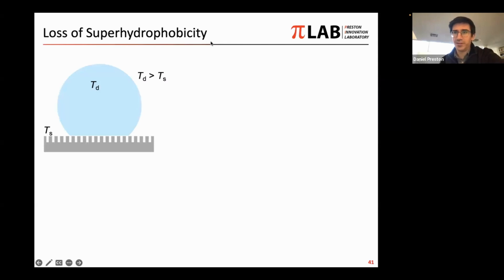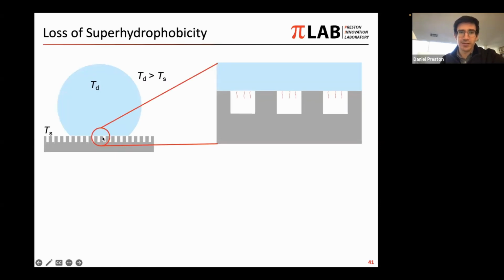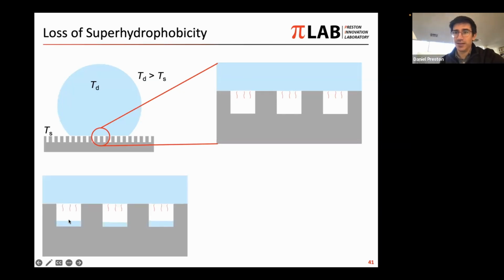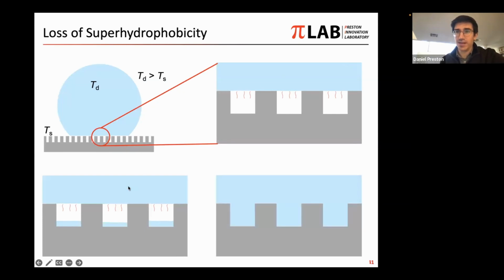And the loss of superhydrophobicity when we have hot impinging water is actually already fairly well understood. So we can zoom in at the structure level here, and we have some hot droplet, some room temperature structures. The hot droplet will evaporate. It'll have some net evaporation of liquid water from the bottom surface, and that may recondense inside of the structures. And if the droplet is hot enough, it may be the case that enough of this evaporation and recondensation occurs such that it fully fills in the structures. And so we're no longer sitting on this nice air layer that helps us have droplet mobility, but instead we have more like an almost Wenzel state. We have this impinged or impaled droplet that's now adhered highly to the surface.